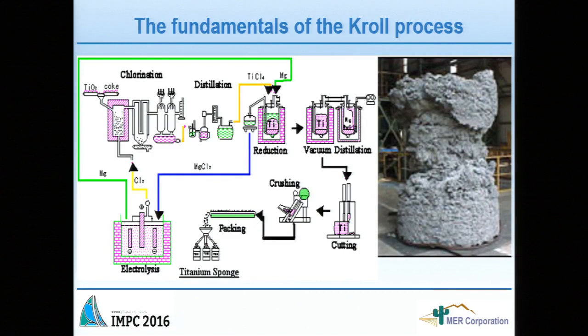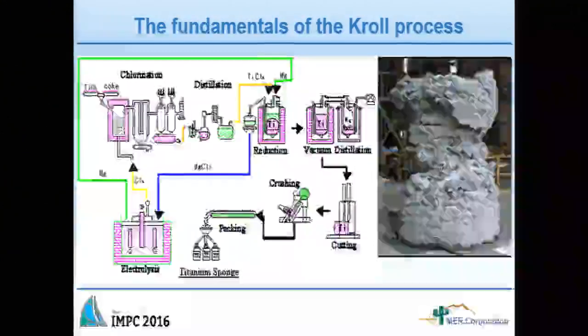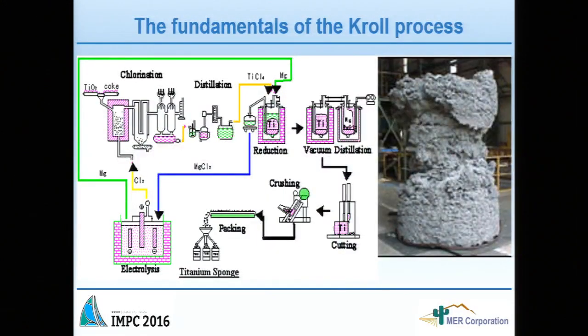So you can see the raw processing steps. This batch reaction takes like 2 weeks and produces about a 10-ton piece that has to be cut, crushed, and sieved into different sizes of titanium sponge. This is our porous, irregular-shaped titanium, so normally it cannot be easily used for additive manufacturing or for powder metallurgy. MER developed a process to actually use the sponge directly in a plasma arc to produce parts. And this is one of the advantages that we developed, because sponge is not as expensive as other alloy titanium.